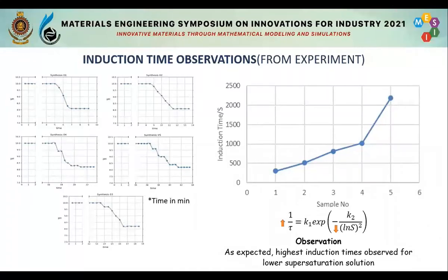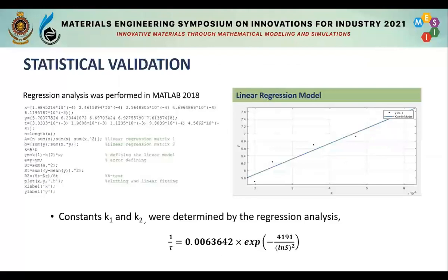Based on these pH curves, we drew an induction time graph for the 5 samples. As you see, the lowest induction time has been recorded for sample number 1 with the highest supersaturation. It is the expectation derived from the kinetic model. Basically, in the statistical validation process, we determined the kinetic constants K1 and K2 from the regression analysis.